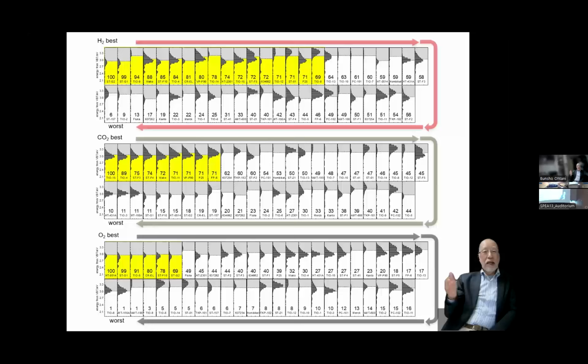In other words, the lower activity samples are not the same. So that means the lower activity has different properties, sometimes lower specific surface area or the band gap or something. So many parameters affect the photocatalytic activity. And for low activity samples, the reason is different depending on those samples. However, the higher one is the highest. The property is almost the same, and that is highest. So that is a very important point.